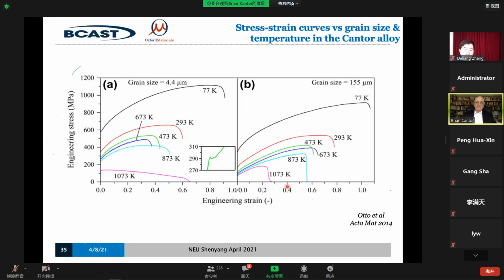And the mechanical properties look like this. So this is the one I've shown you before. Sorry, this one here. Room temperature. The room temperature behavior of the Cantor alloy depends on its grain size. It's not quite so good at a big grain size. It's better if you have a smaller grain size than 4 microns, if you go to 1 micron. So typically the yield strength is about 400 or 500 megapascals. It's got a ductility of 50 or 60%, depending in detail on the grain size and the temperature, because if you go to lower temperatures, it's got even more ductility and a higher strength. But it's typically around half a gigapascal to 2/3 of a gigapascal yield strength, between 2/3 and 1 gigapascal ultimate tensile strength, and between 50 and 100% ductility.